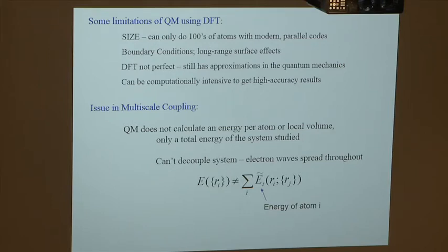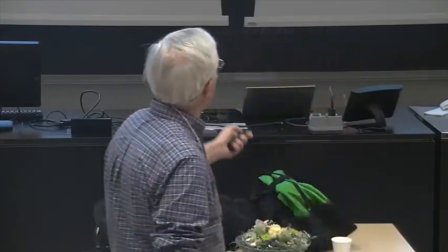The boundary conditions: we deal with boxes. Typically, if we use Fourier series, we want to do periodic systems. Well, cracks aren't periodic, dislocations aren't periodic. So if you want to do something that's not periodic, you end up with boundary condition effects. And you have very, very small systems that are only tens of angstroms in dimension, and you have boundary condition effects. So you have to be very careful.